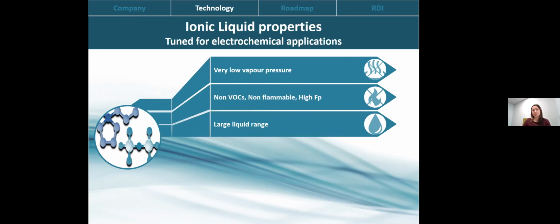They have a very large liquid range. Of course, when you talk about ionic liquid, usually you can have about -5 to 100, 120 degrees. But when you can mix them, which is extensively studied by Professor Passerini's group, where they have eutectic mixtures of ionic liquids, you can also extend the liquidus range to -80.